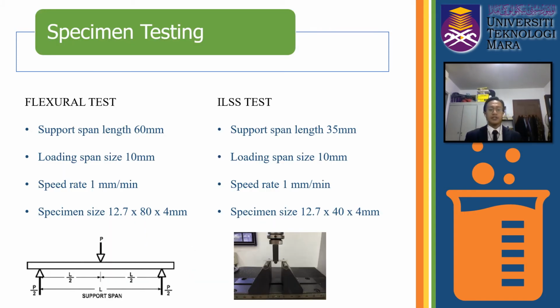For the specimen testing, I have used two tests, which are the flexural test and ILSS test. For the flexural test, I will cut the specimen that I have made using my previous mold in the size of 12.7 mm times 80 mm times 4 mm. The support span length is 60 mm and the loading span size is 10 mm and the speed rate that I use is 1 mm per minute.